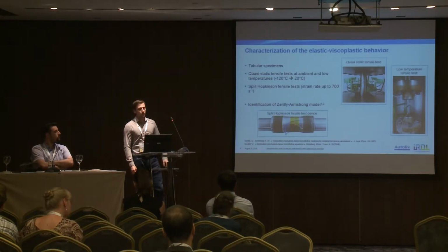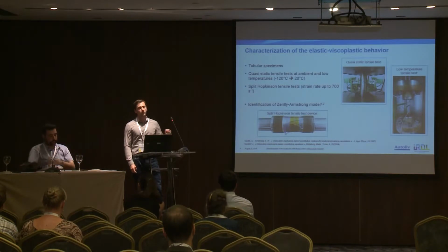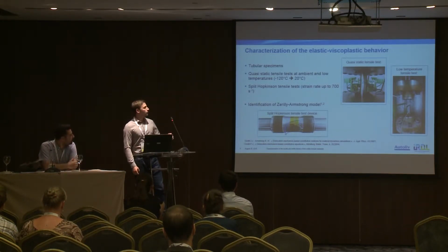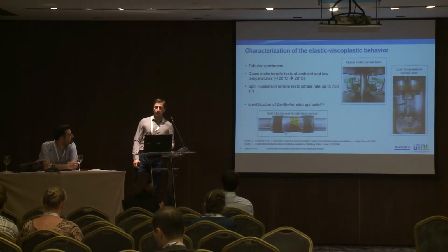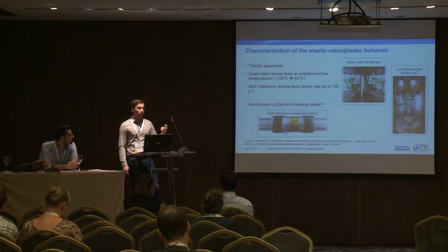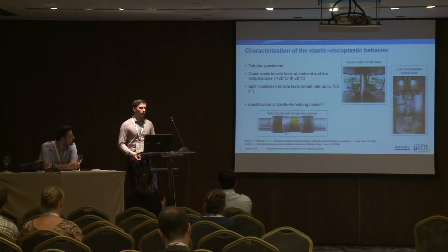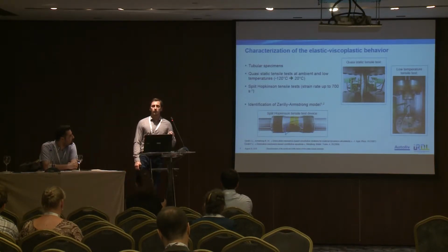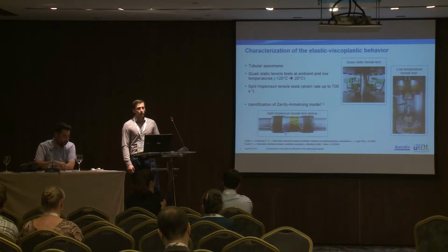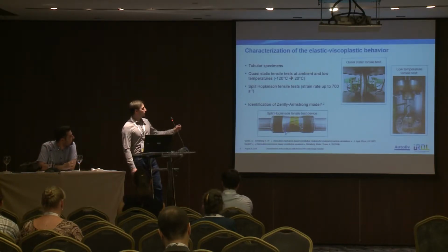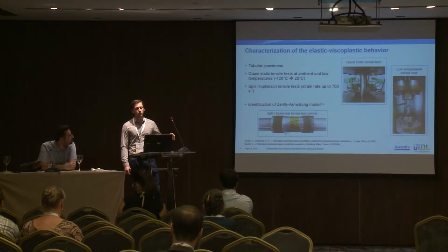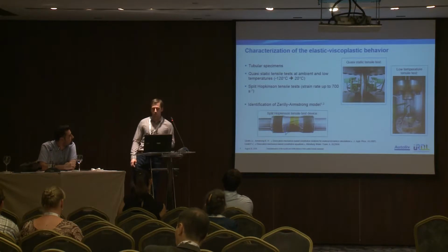First of all, I can only work with tubular specimens. Why? Because the steel supplier is not able to produce the same material in a flat shape. So consequently, for quasi-static tensile tests at room temperature and low temperature, I have to use, of course, tubular samples with a defined geometry. Also for Split-Hopkinson tensile tests, which are made in order to characterize the strain rate sensitivity of our material, we have to deal with tubular samples. That's why we have developed in my laboratory a new methodology in order to apply tubular samples to Split-Hopkinson tensile tests. If you have any question, I can answer at the end of this presentation.